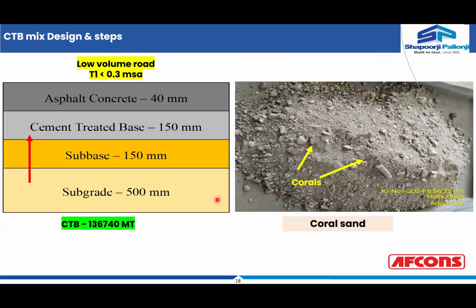Now, this is the filtered, processed coral sand which was available there in Hulhudhoo city, which is near to Addu City. This is the location of that city, and this sample was collected in 2024. And this is the material which is being introduced into the cement treated base layer. Whereas the demand for the cement treated material was close to 136,000 metric tons, and since the requirement is more, the replacement will add value to these particular areas.